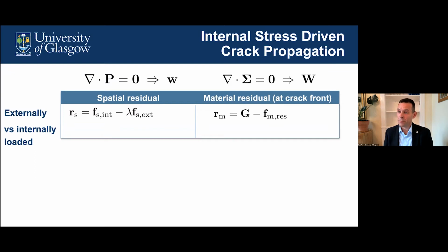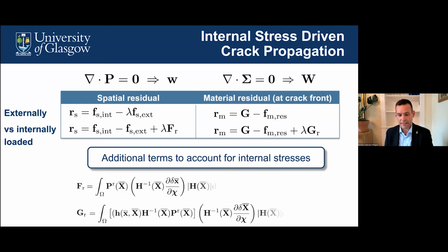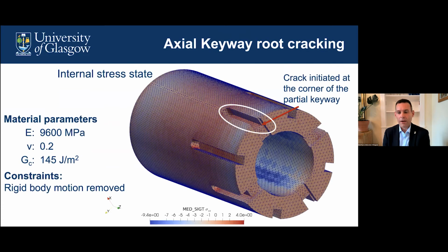But when the problem is driven by internal stresses, then we have to change the equations that we are solving, and we're now scaling the internal stresses in order to drive the crack propagation. And so we end up with a different system of equations that we're trying to solve. And as you can see, the additional terms that come from that are fairly complicated. So let me just show you an example of this in practice.